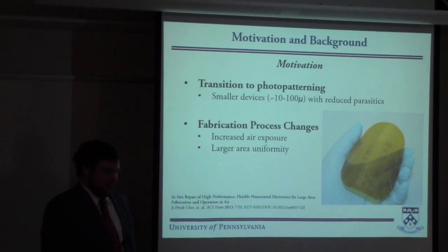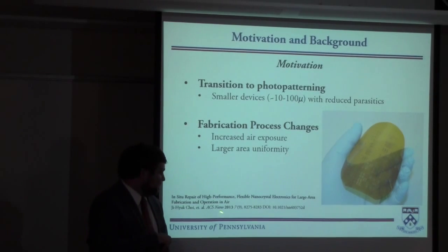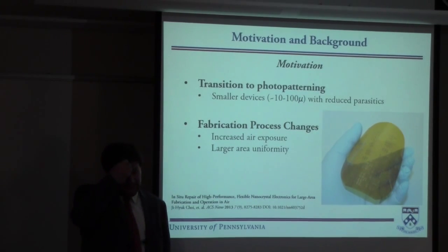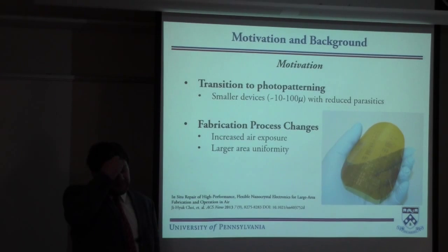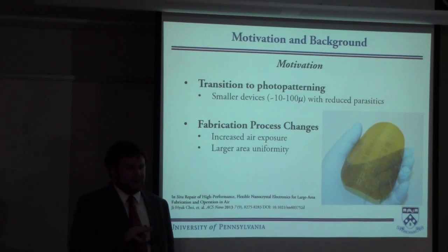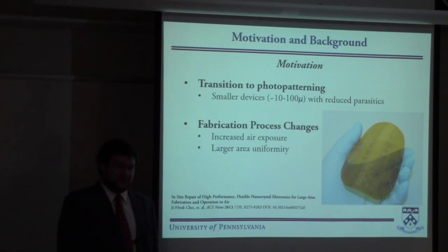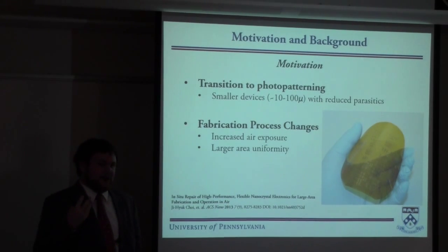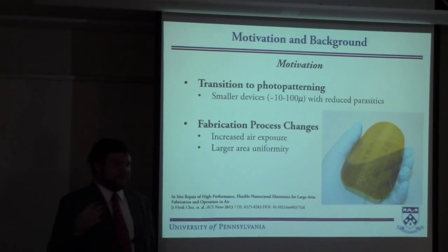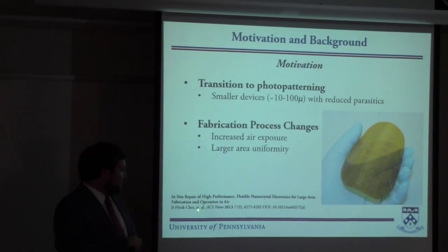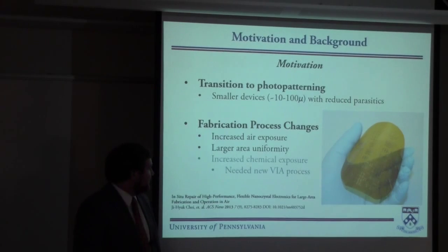So this became a solved problem in 2013 with some work that was done that I'm not going to dig into because it's far too complicated, on the effects of indium doping and the recovery effects of the indium actually kicking oxygen off of the surface of the particles and recovering these devices back to functionality. So this became a solved problem in 2013.